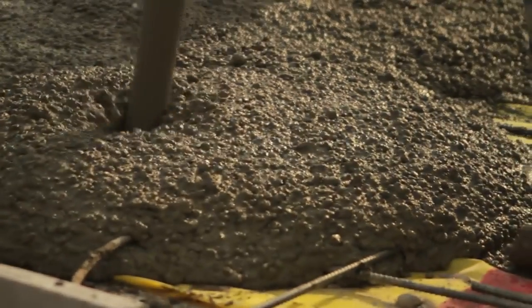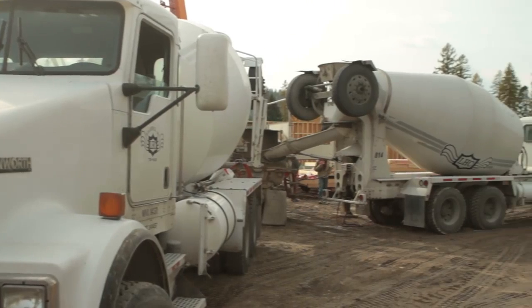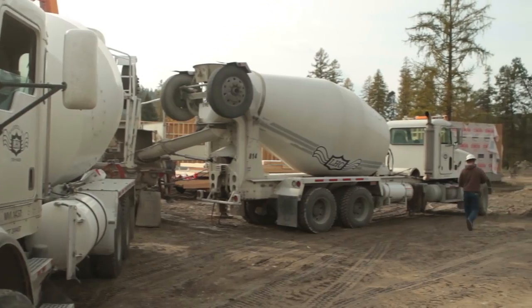But not everything can be so massive that it doesn't experience any tensile stress. Modern structures like highway overpasses and skyscrapers would be impossible without reinforcing the concrete. So generally, we like our concrete to be more viscous or soupy — it's easier to work with, flows through pumps and into complex formwork and around the reinforcement much more easily. So one way we get around this water content problem in the modern age is through chemical admixtures — special substances that can be added to a concrete mix to affect its properties. Water-reducing admixtures, sometimes called superplasticizers, decrease the viscosity of the concrete mix, allowing concrete to remain workable with much lower water content.